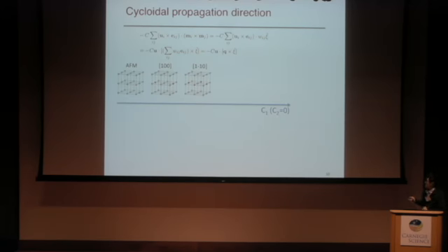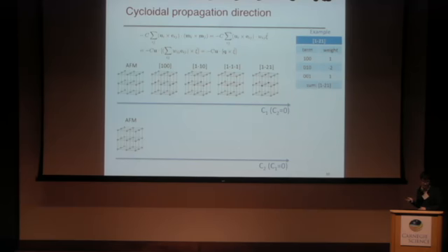And for 1, minus 1, 0 cycloids, we have 4 contributions of the same weight, because this combination of the same weight, which could be plus or minus, can give us this weighted sum in this Q direction. And then for the 1, minus 1, minus 1 cycloid, we have 6 contributions of the same weight, and they can give us this Q vector. The last one is the 1, minus 2, 1 cycloid. We still have 6 contributions, but along the y direction, the weight is doubled. So we have the weighted sum in this Q direction. And that's how it works for the first neighbor terms.